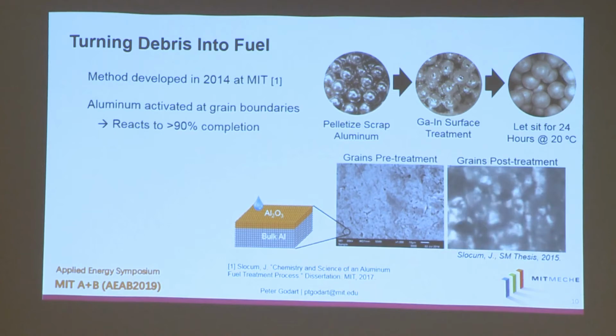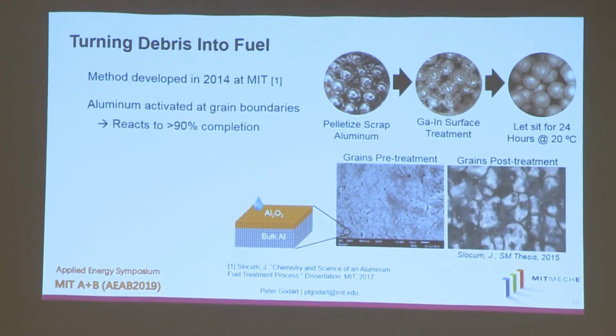So how do we take those pellets and turn that into a fuel? Well, we use here at MIT a process that was developed in-house a couple years ago, where we take that pelletized scrap aluminum, we treat the surface with a small amount of gallium and indium, and then we just let it sit out for 24 hours or so at room temperature. And ordinarily, aluminum has this oxide layer on the outside that prevents it from reacting with water. But what we've found is that using this process, the gallium and indium actually have the capability to disrupt this oxide layer at the grain boundaries where this gallium and indium eutectic sits. And you can see in this microscopic video here that hydrogen is being evolved at the grain boundaries. And in fact, this process allows the aluminum to react to over 90% completion.